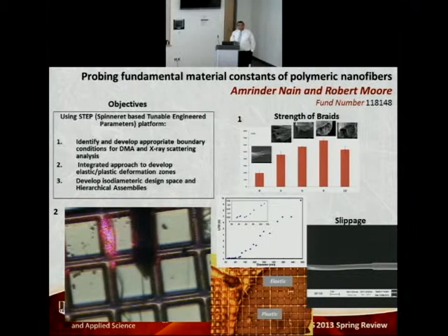We wanted to look at, for an amorphous polymer system like polystyrene, when you start making fibers which approach 100 nanometers or lower in diameter, do you start seeing short chain ordering at the single fiber level? A 100 nanometer fiber you can't obviously see optically. So the big challenge here is how do you go about applying boundary conditions to them? And can you use existing tools to measure the orientation of the chains?